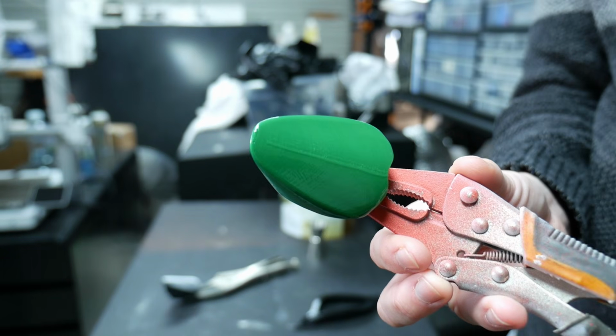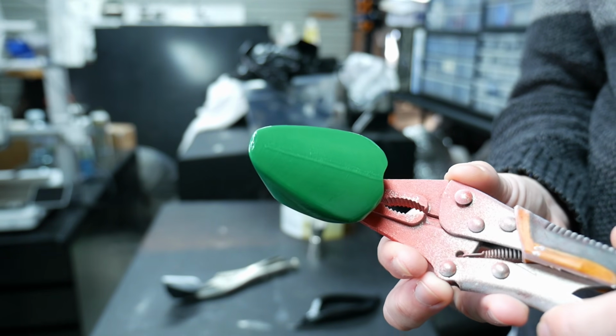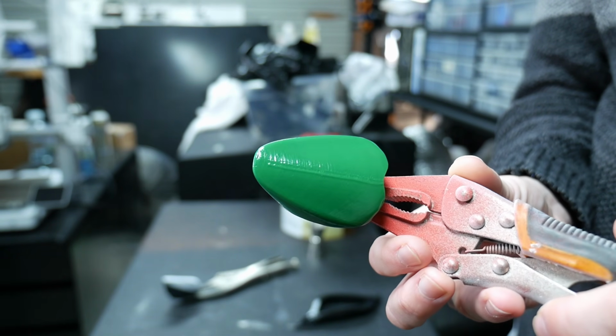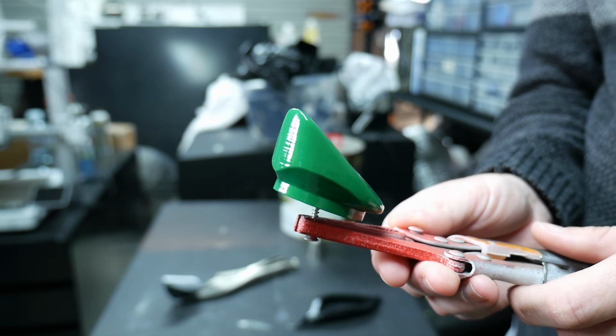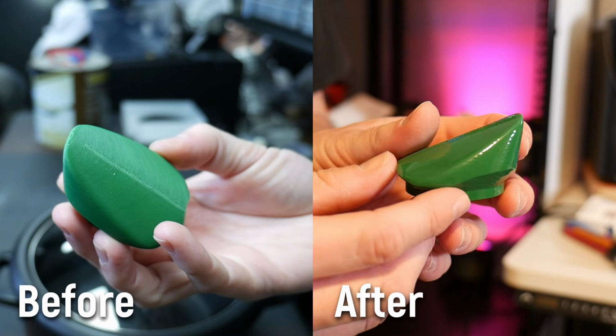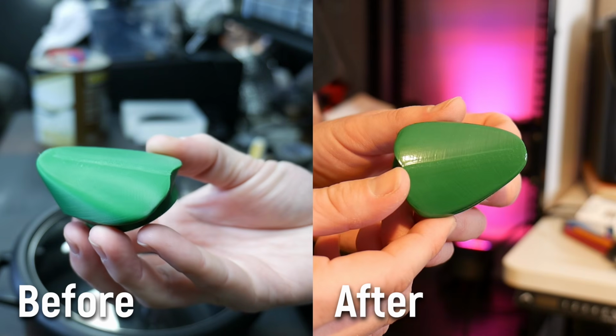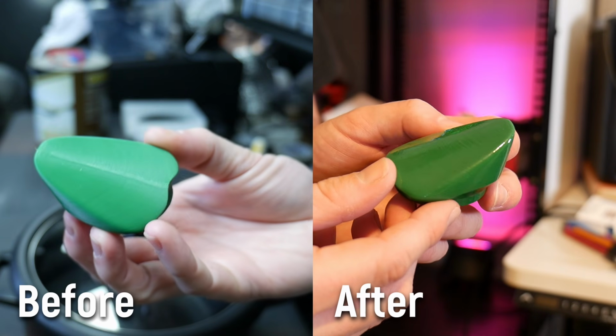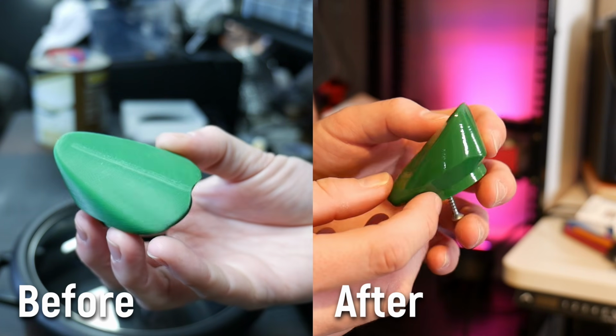I generally found that they needed a good 24 hours or so before the acetone in the plastic evaporated away and the surface would harden again. Acetone vapor smoothing using a rice cooker is the literal definition of a 3D printing hack. It's no magic bullet. The layers that were smoothed the best were the finely stacked vertical surfaces, and the sloped surfaces still have visible stair stepping.